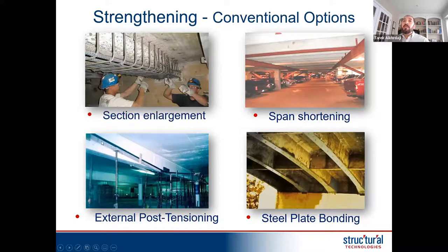And then the third technique is external post-tensioning, where we use high strength steel cables and pre-profile them along the elements, like you see in this photo, a beam with the post-tensioning anchored at high points, and a low point at mid-span that goes high again at the top of the column. By reprofiling the post-tensioning, when you stress it, you can create an uplift force that overcomes additional loads that you may add to the structure or deficiency in the existing structural elements. This technique has been used a lot, and we still use it within the repair and strengthening industry.